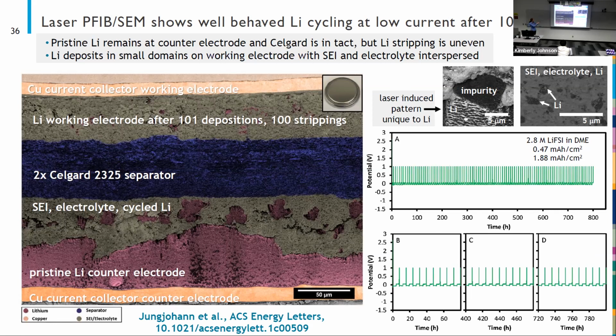So we would zoom in on these images. Katie would spend a lot of time on this. And she would find all of the areas where we actually had lithium metal present in a bulk form that showed this fingerprint pattern. And you can see that there's also this blue region that is our separator that we can also pick out pretty clearly. But then there's all this other gray junk that we can't really assign.